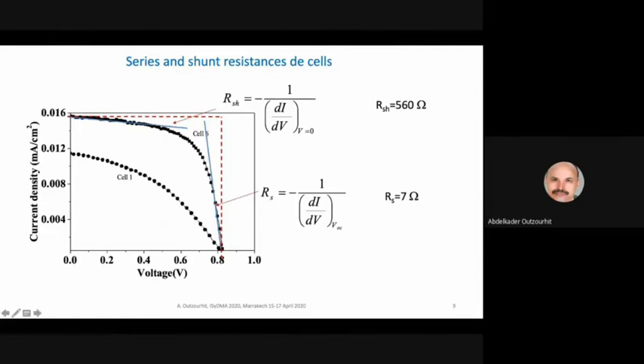This value of the series resistance is a little bit high for typical solar cells, and it may be due to the underlying sheet resistance of the FTO contact, or the FTO-coated glass substrate. So we have to improve those values in order to reduce the series resistance, in addition, of course, to the contact resistance, since we also use aluminum, and aluminum may present some interface oxides and so on that increase the series resistance a little bit.